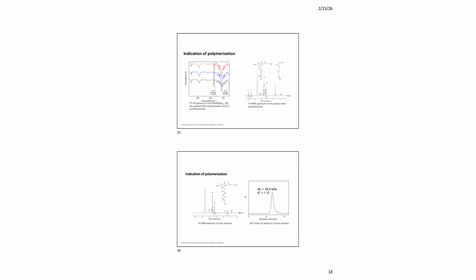Evidence of polymerization was collected using several techniques. FTIR spectroscopy shows the disappearance of the carbon-carbon double bond peak of the monomer after polymerization. The proton NMR spectrum of the raw product confirms the conversion of monomer to polymer. After purification, the NMR spectrum of the pure polymer is clean, and GPC analysis shows a well-defined polymer with a molecular weight of 28.6 kilodaltons and a low dispersity of 1.12.